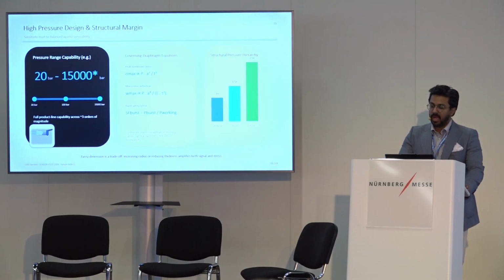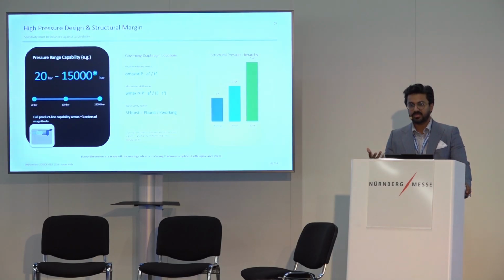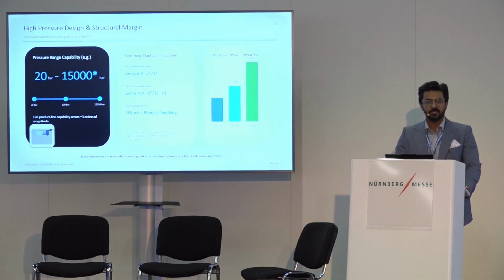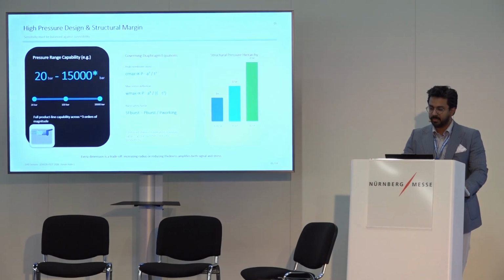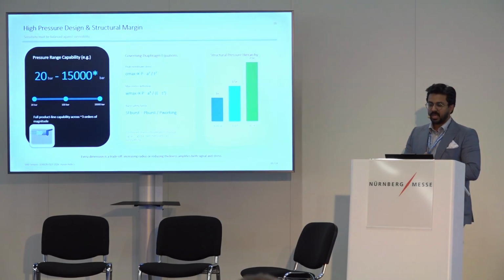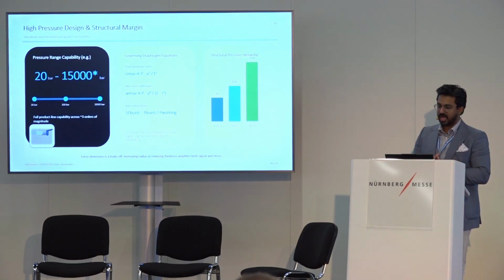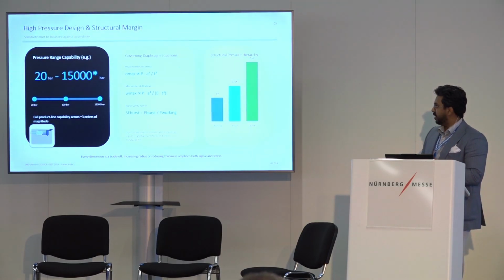Designing a high pressure diaphragm is a constant fight between signal and survival. If you look at the two equations, when designing the sensors, we have to balance how much we are stressing the substrate. Is it in one region or is it spread out? You have to look into that and count it as a variability when designing your sensors, aligned with subsequent tests and experiments. Peak stress scales with pressure and gets much worse as the diaphragm gets wider or thinner. That explains the first equation.